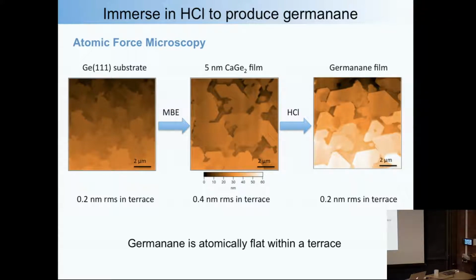But we looked also with atomic force microscopy, because once you see the nice RHEED patterns, you want to do the AFMs. So we look at the substrate, and the substrate is never perfectly flat. So there's a half-degree miscut. On this one, it turns out the terrace widths correspond to 0.2 degrees of a miscut off of 111. And then you do the MBE growth. What happens actually is the terraces are getting bigger, so this material wants to make it flatter, right? So this is the calcium germanide. And then you dunk it in HCl, and then, yeah, it looks really nice.